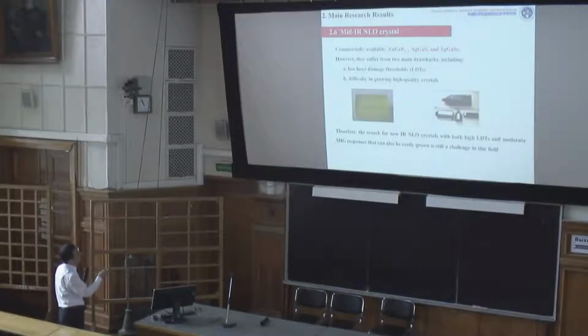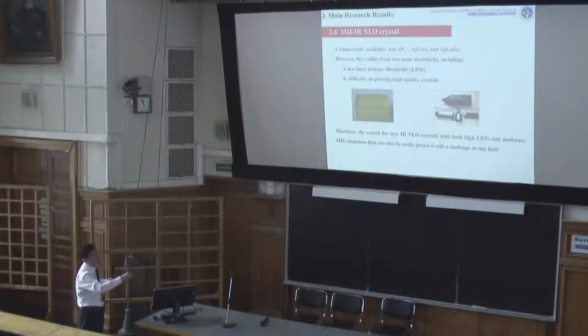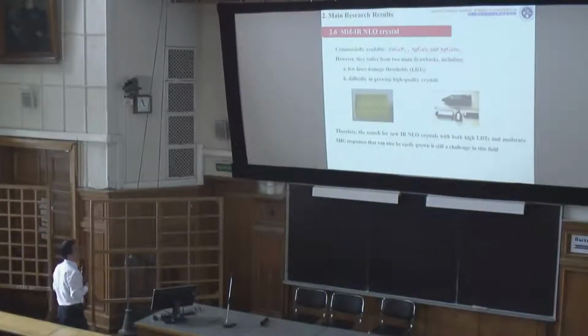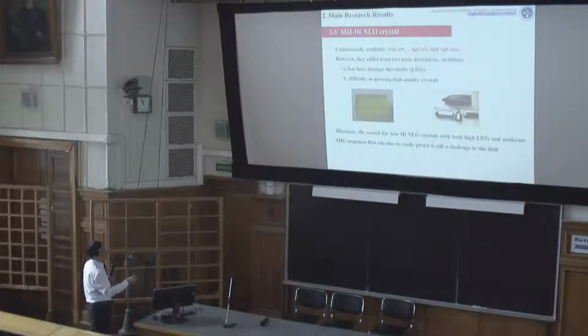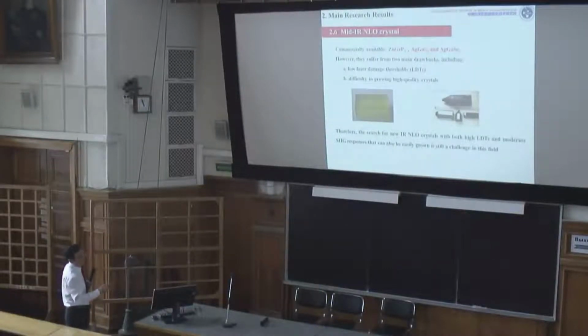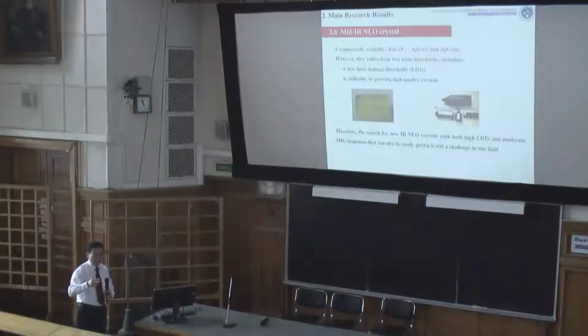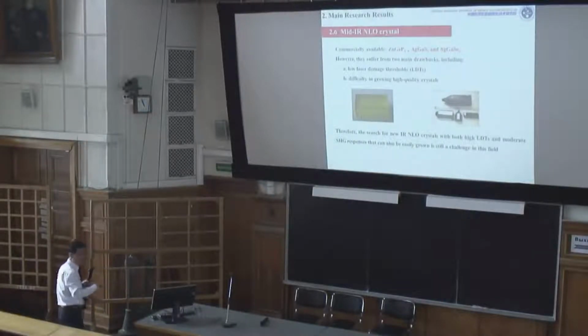And also, we are also concerned with nonlinear materials, especially in the infrared region. Commercially available IR nonlinear materials are three compounds: first one is ZGP, AGS, and AGSe. These materials have wide application in the world. Only three compounds, three crystals. However, these crystals suffer from two drawbacks. One is low laser damage threshold. The second is that it's difficult to grow crystals, because this kind of material should be grown in a closed system, cannot be exposed to atmosphere. So it's difficult to grow crystals.